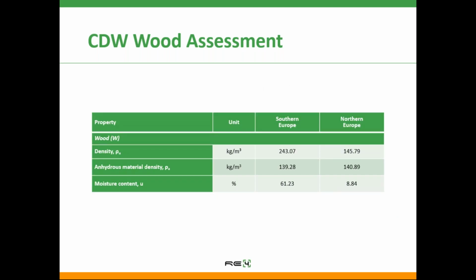In the table shown here are reported the calculated average values of density and moisture content on 5 different samples for each source of material. The density of the wood fraction is obtained by the ratio between the mass of wood particles and their apparent volume at a predetermined moisture content value. The moisture content in the wood fraction was calculated as the ratio between the mass of the water in the wood fraction under examination and the mass of the same anhydrous wood fraction. In order to obtain the anhydrous wood fraction, the execution method has been carried out until mass stabilization. The high difference in terms of density is dependent on the difference in moisture content of the two wood fractions, as confirmed by the anhydrous materials.